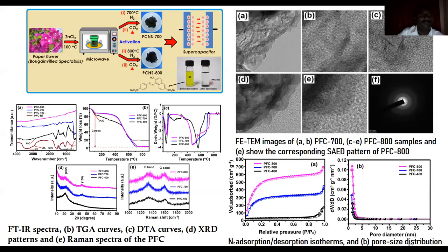The botanical name of this paper flower is Bougainvillea spectabilis. I collected the paper flower, dried it, and then mixed it with zinc chloride at 100 degrees centigrade in microwave radiation. There were two heating temperatures, 700 and 800 degrees centigrade. During heating I used physical activation, meaning carbon dioxide was used for activation at higher temperatures like 700 and 800 degrees centigrade. This final composite is used for dual application: one is supercapacitor, another is dye adsorption studies.